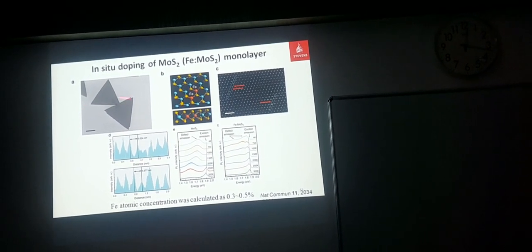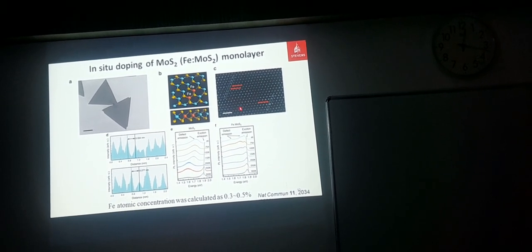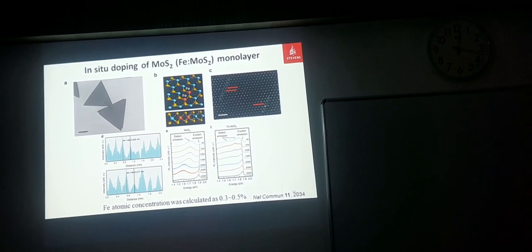This is a flake of two-dimensional material, molybdenum disulfide, in a scanning electron microscope image, and this is the structure. What we did here was replace some molybdenum with iron. Here you can see the high resolution microscopic image. This side is the iron, and this side is the molybdenum. We also used some other techniques just to confirm the material's properties, but I am not going into those details.